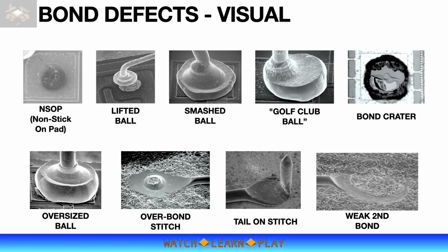Smash ball is another defect, which is simply an overbond. If all bonds have the same manifestation, in most cases this is due to bond parameters being too high. Another possibility could be the bond height is not learned properly. In this case, you will see a smash ball or overbond on random wires. Die tilt caused by an improper die-attach process can also lead to the same problem. Indication of this is the problem is only happening on some devices and it is localized within the device.